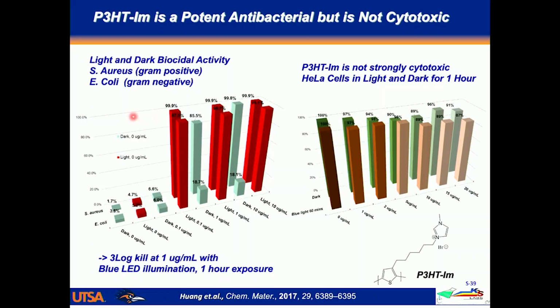And what I'm showing here is different concentrations of the polyelectrolyte, 1 microgram and 10 micrograms up here, and red means light exposed, and green means no light. And you can see that at about 1 microgram per milliliter, we're getting up to close to 99.9% killing effectiveness. That's kind of the gold standard for bacteria. It's called 3 log kills. So if you get 99.9, you're doing pretty well.